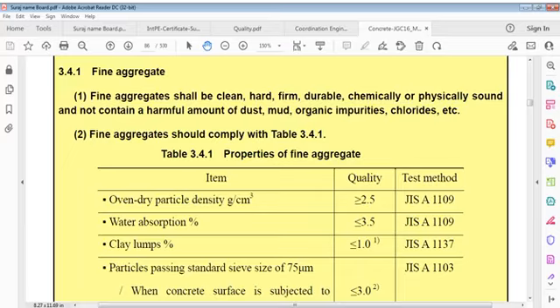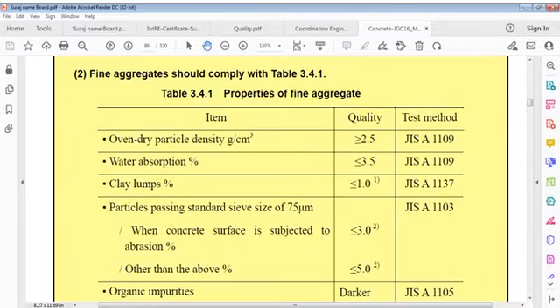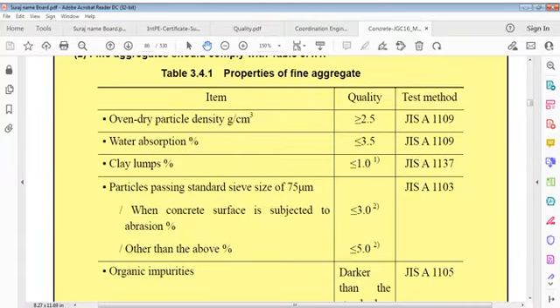Fine aggregate should comply with the table of properties of fine aggregate. Oven dry particle density in gram per centimeter cube is more than or equal to 2.5, that is the quality. Then water absorption percentage less than or equal to 3.5, and clay lumps less than 1.